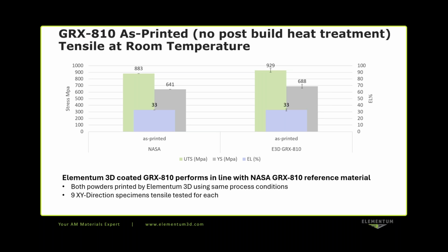And you can see that ultimate and yield strengths are very comparable. If anything, the Elementum material is in line or even exceeding the reference properties, which is great, and the elongation is spot on in both cases. One other comment on here is that NASA HIPs everything for additive. The material performs great even without a HIP. It's really an optional HIP, in my opinion, that it performs great with or without a HIP.